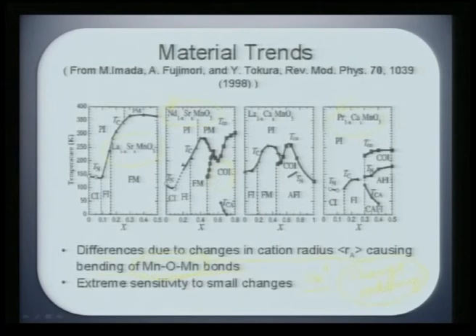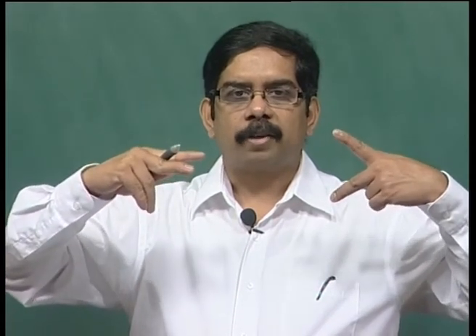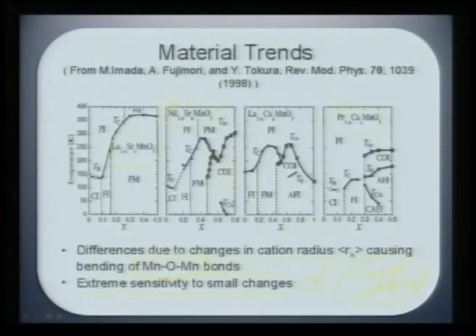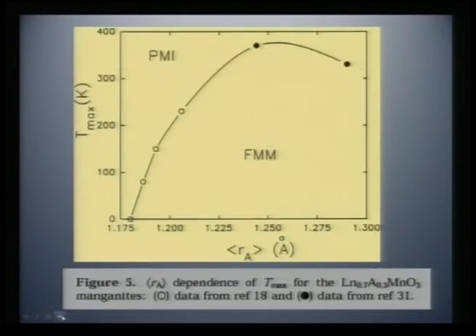In other words, there is a sudden twist in the Mn3+ and Mn4+ orbitals and they become orthogonal. As a result, there is no collinear magnetism and there is no exchange transport of electrons. As a result, this system suddenly transforms to an insulating state. So, it is an extremely sensitive composition, where small changes bring about such a drastic change.